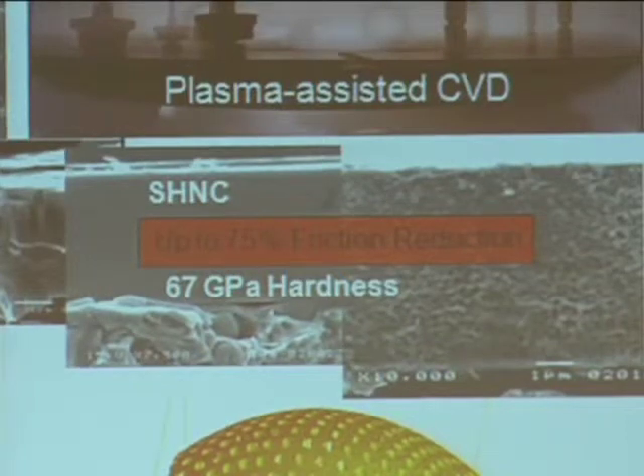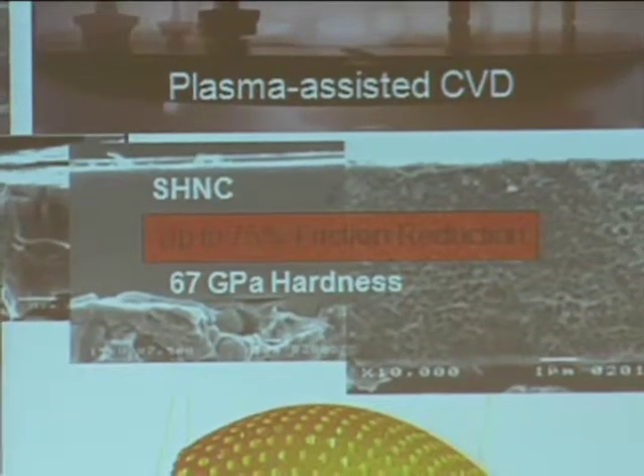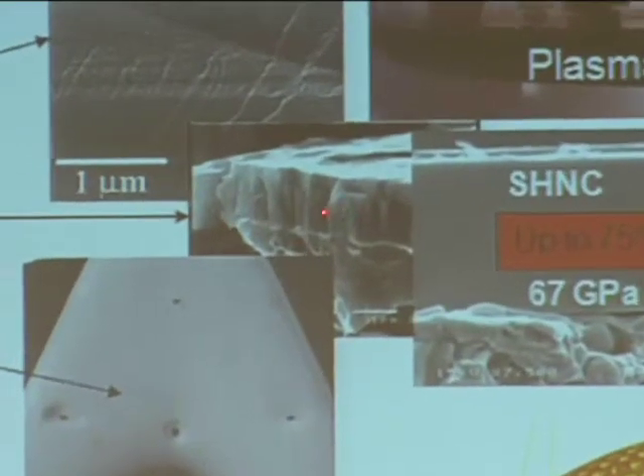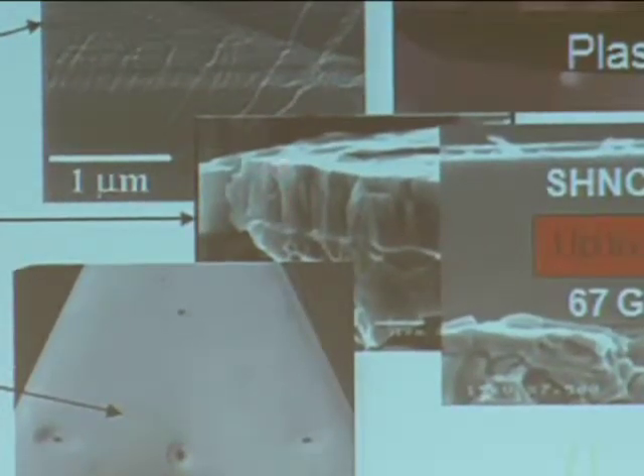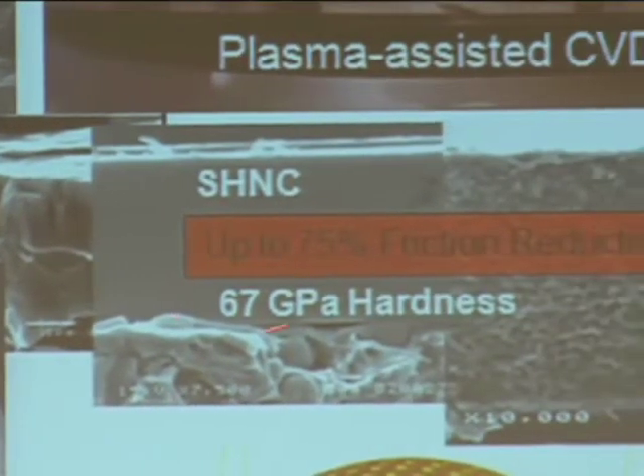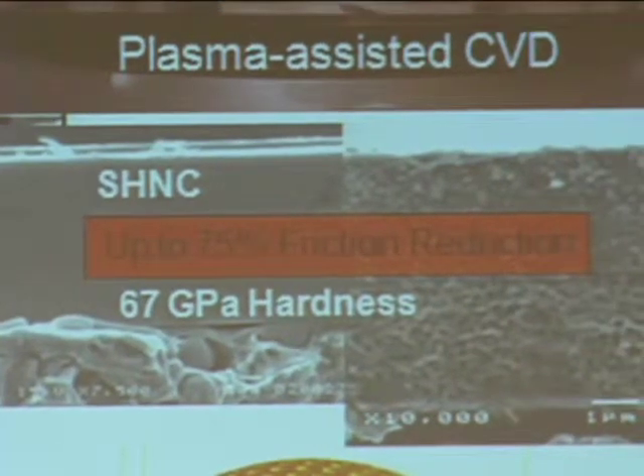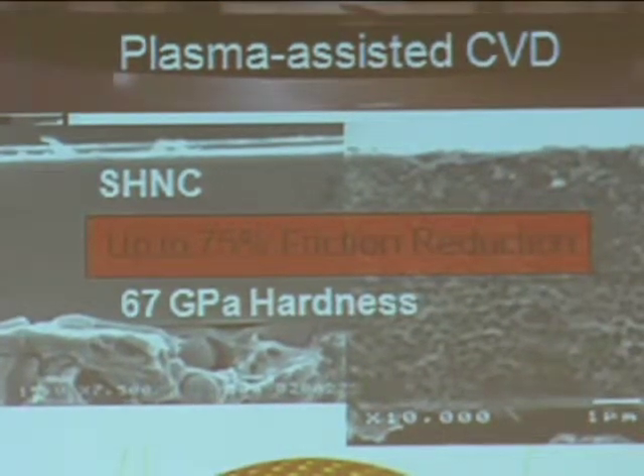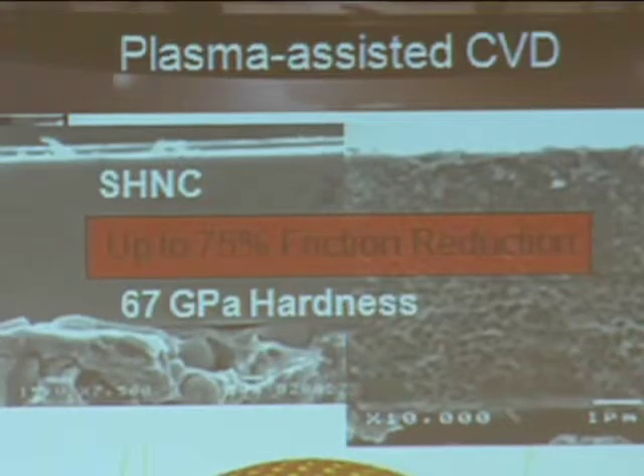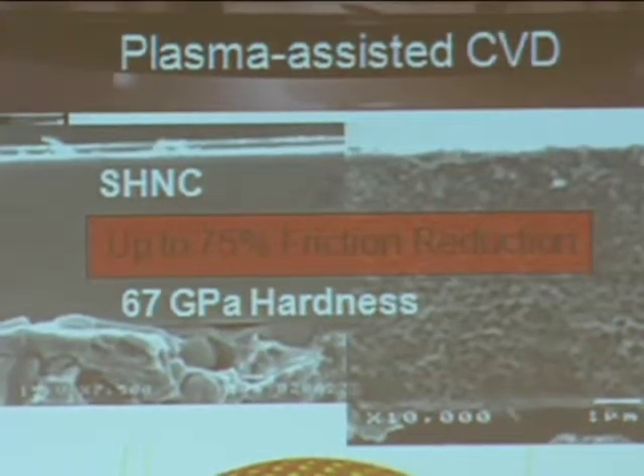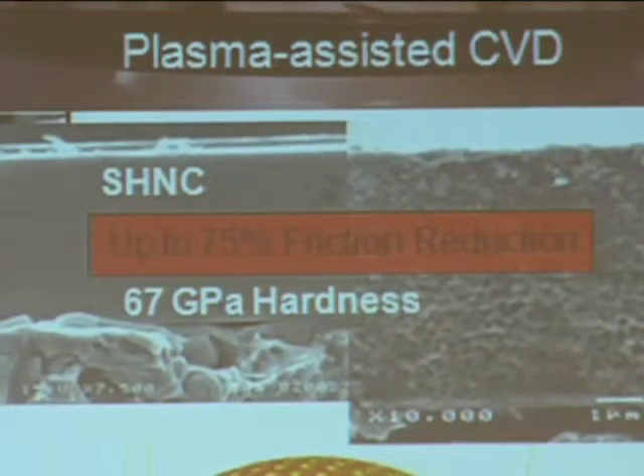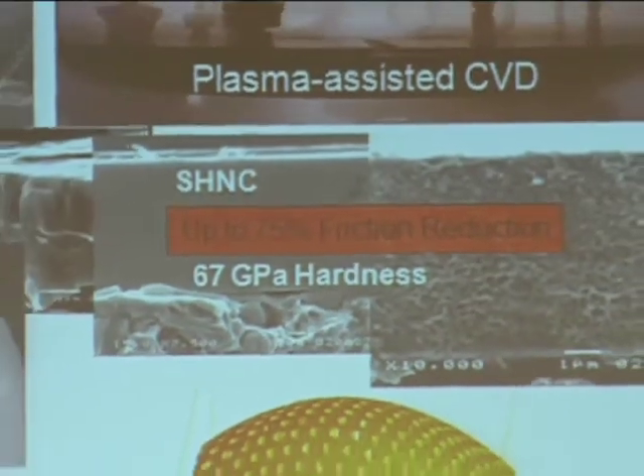We've been able to engineer the microstructure of very thin, hard nitride coatings, where we go from a weak columnar microstructure to a very dense nanocomposite structure. These particular coatings can be quite hard. Hardness is up around 67 GPa. And by controlling the composition of the coatings and the additives that you put in there, you can design those in such a way that they interact very beneficially with the additives that are found in many oils.